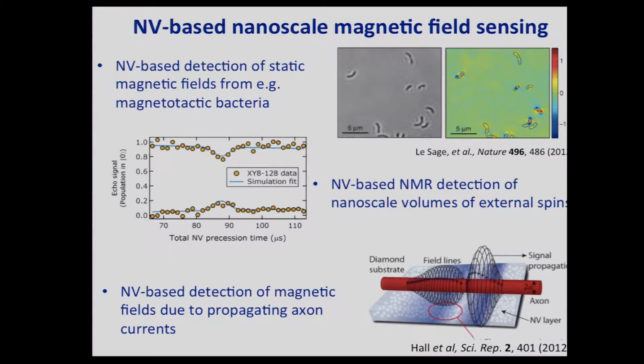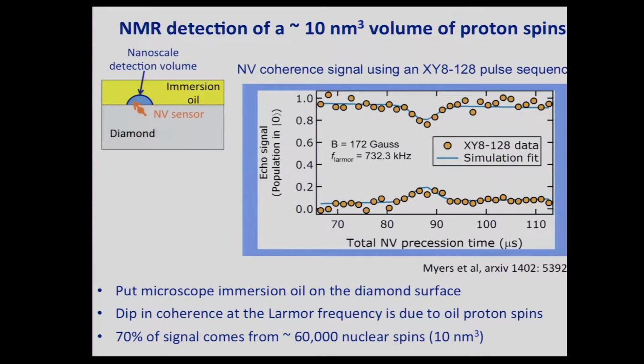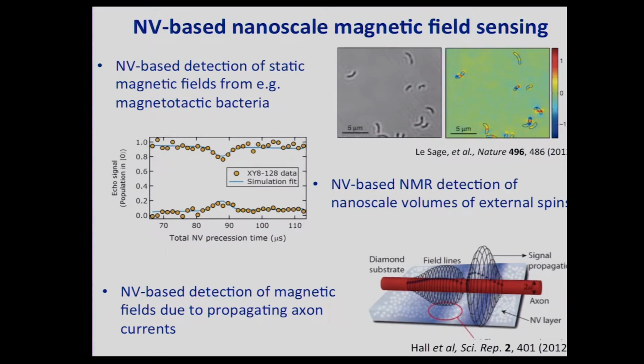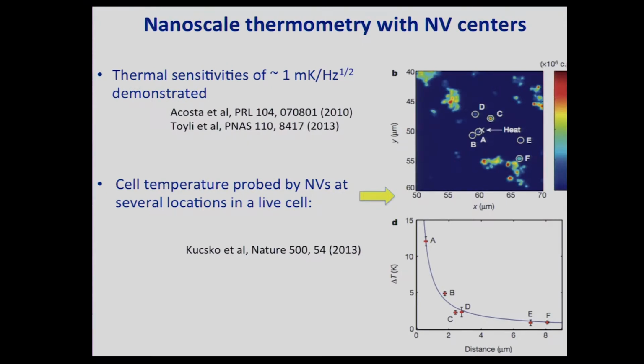It's not just surface, though, because in this experiment we showed that we can make NV centers as little as 3 nanometers below the surface that still have good coherence properties. And I'll actually talk about the issue of using nanodiamonds and making better nanodiamonds shortly. But so far, most of the detection sensing measurements have been done with bulk diamond. There is this one exception, and also another demonstration of another type of sensing.